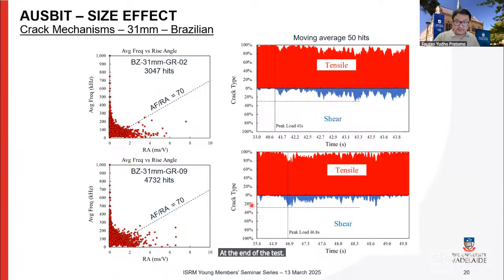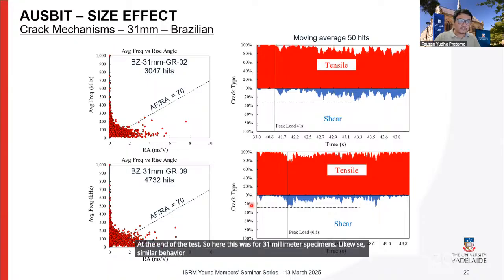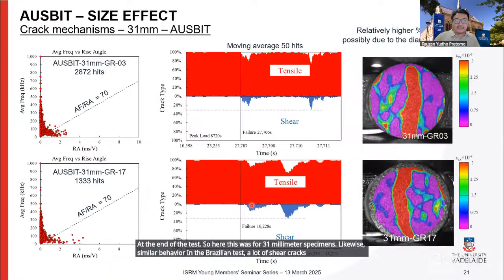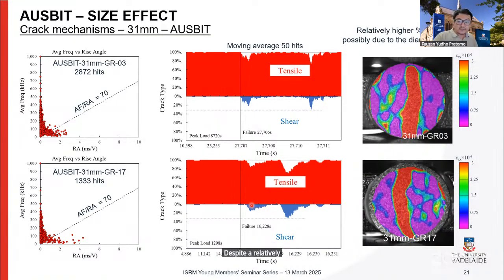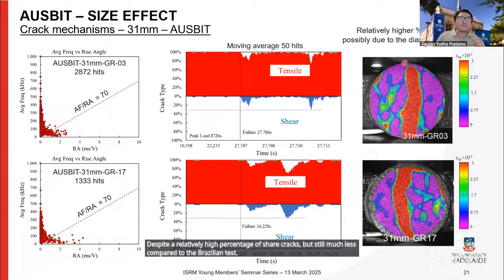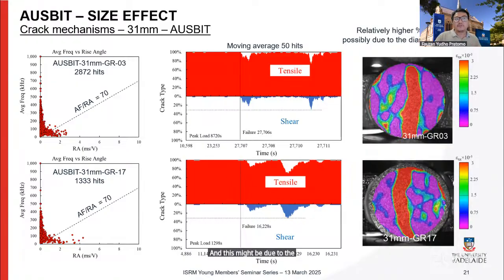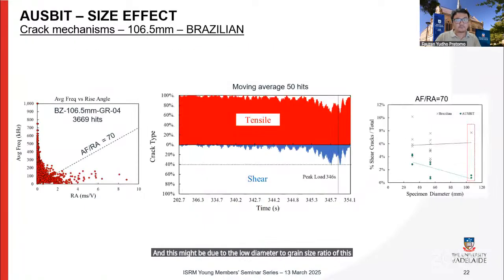So here, this was for 31 millimeter specimens. Likewise, similar behavior in the Brazilian test, a lot of shear cracks. And in AUSBIT, despite a relatively higher percentage of shear cracks, it is still much less compared to the Brazilian test. And this might be due to the low diameter to grain size ratio of this size of specimen.